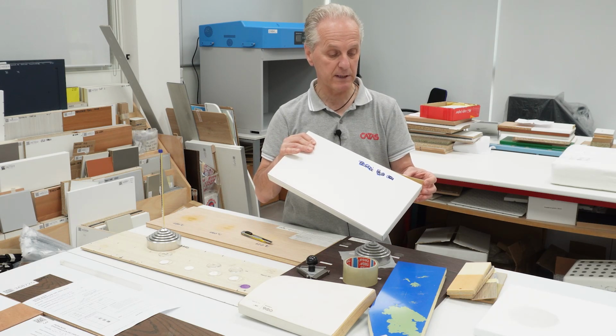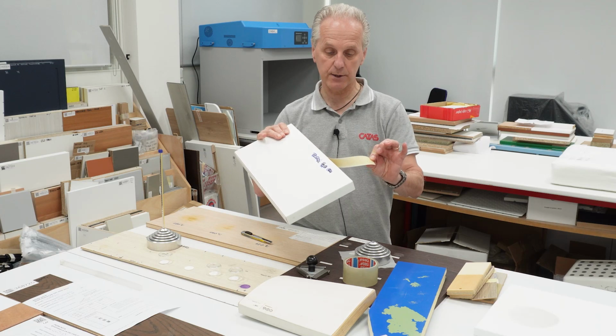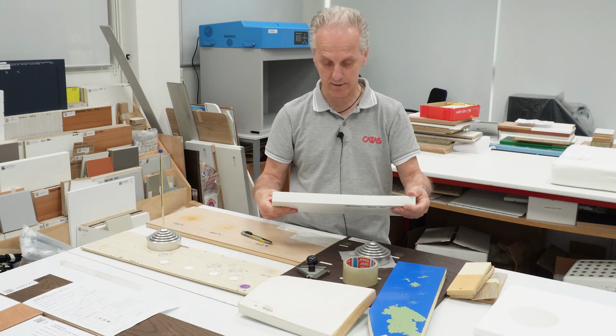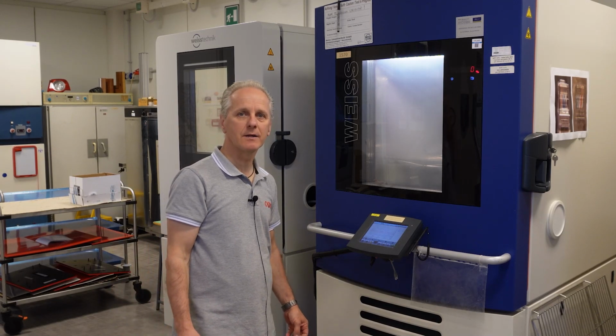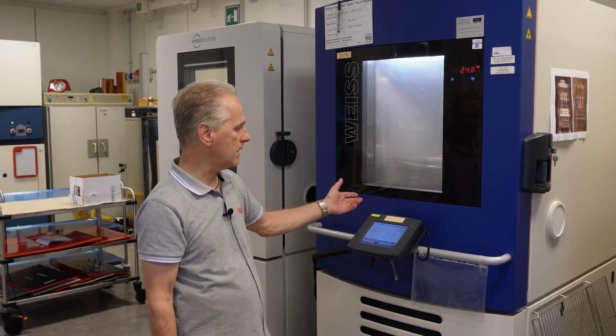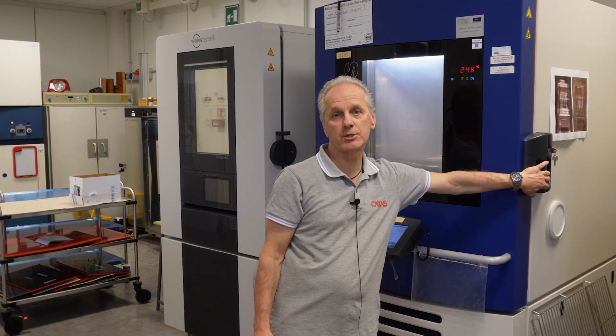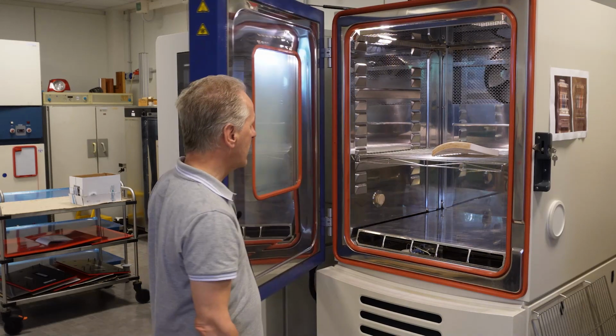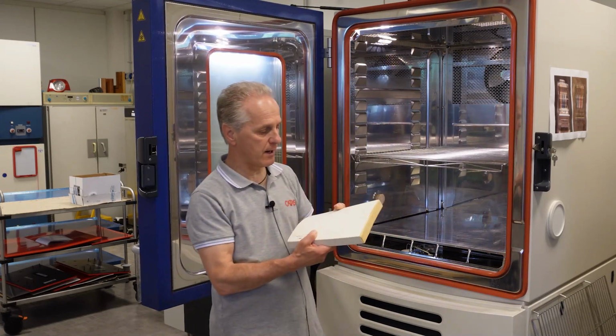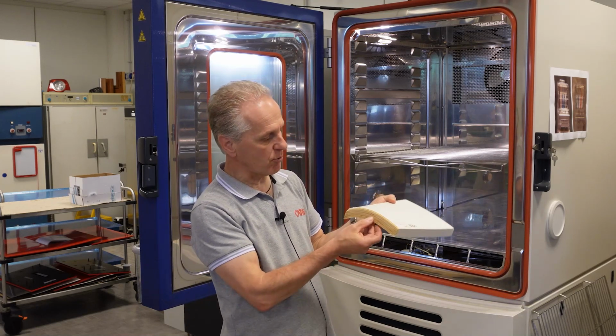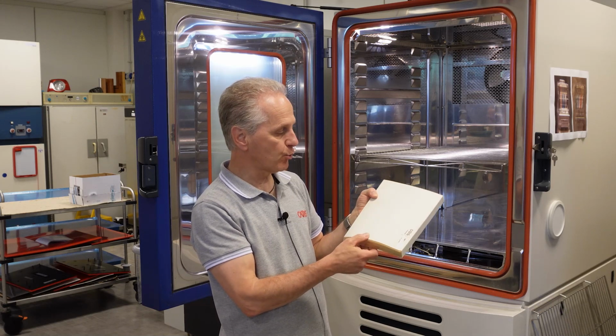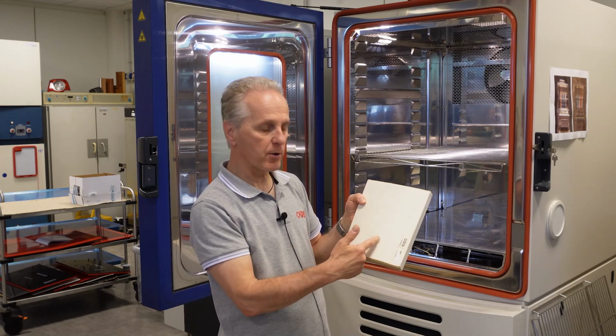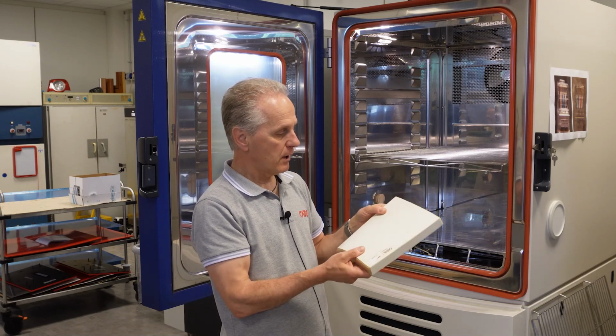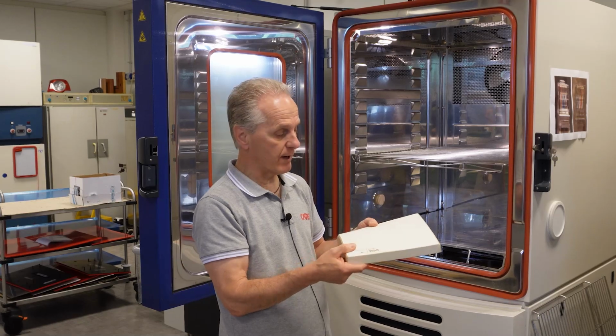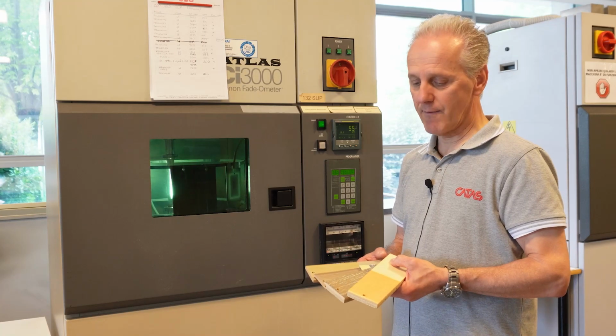In this case, we can observe that after a relatively low temperature, the adhesive part has collapsed and the edge is out. This is the aging area. We are standing in front of a climate cell, which we use to run temperature sudden changes tests. We can see here that there is a panel at the end of the test. This multi-layered panel, varnished, presents some ruptures of the varnish. Due to sudden temperature changes, the varnish coating was not able to bear the tests and got broken.